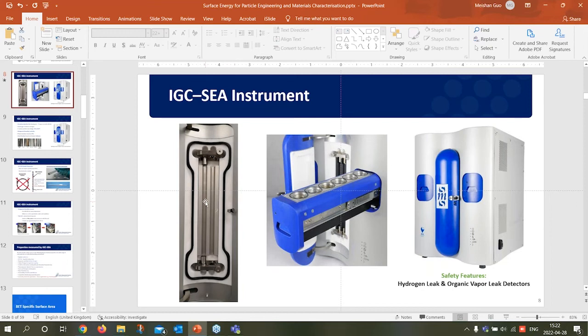So we did some measurements of other high surface area material, with different treatments, with more than 600 square meters per gram. Then we can still clearly see the surface energy differences between the different treatments. That's no problem. Thank you.